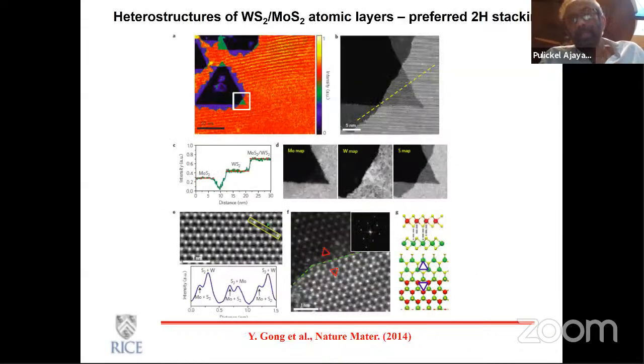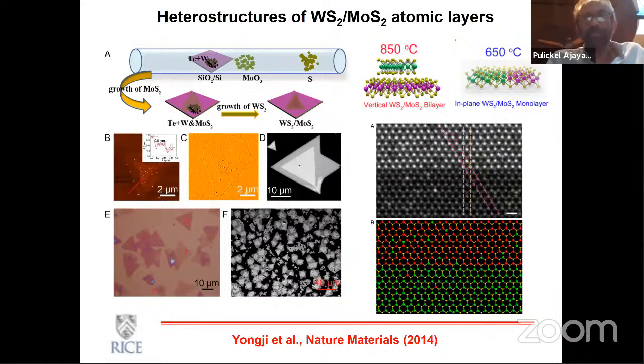And out of plane, as I said, one could have different types of stacking: the preferred 2H stacking, which leads to a more semiconducting type of material, or what we call the 3R stacking. So there again, stacking could be quite complex when it comes to these materials. So again, a lot of microscopy that we have done over the years shows that under certain conditions you can actually get these preferred 2H stackings, or under lower temperature, one could get systems that grow in-plane heterostructures.